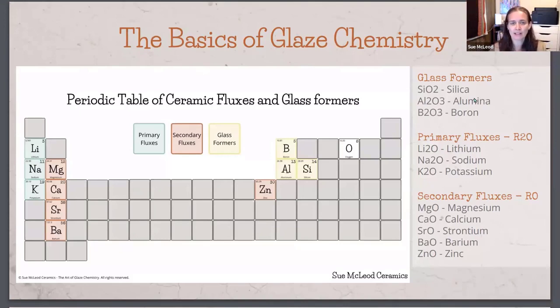So how do we lower the melting temperature of silica? We do that by adding fluxes. And fluxes can be divided into two groups. The primary fluxes are referred to as the R2O. That's just shorthand for the R can represent any element that takes this format. So all of the primary fluxes are in the first column of the periodic table: lithium, sodium, and potassium. The secondary fluxes, the RO, so it's one element bonded with one oxygen, so magnesium, calcium, strontium, barium, and then also zinc, which is over here.